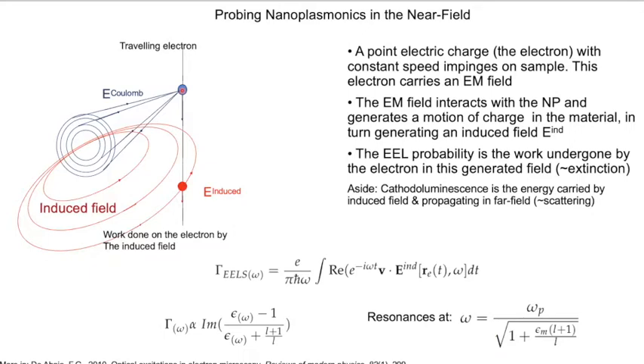And then that polarization generates an induced field here that I have in red, and that induced field in turn acts back on the electron that's traveling down the column and can do work against this electron. All of this process, again, really only depends on the plasmonic properties of the nanoparticle. And so by having electrons travel around the particle, we're able to sense basically the polarizability at a certain energy for these particles.